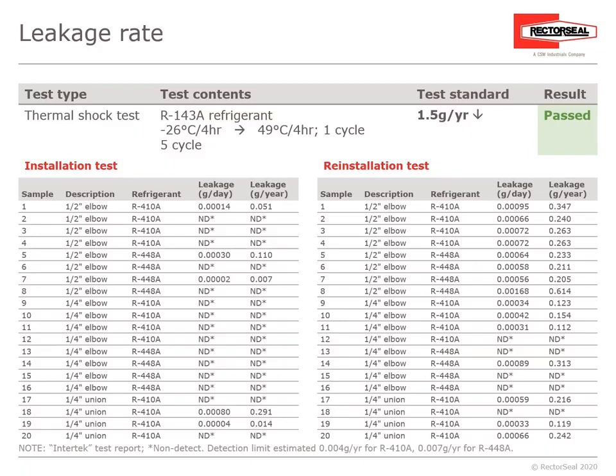Then we took our release tool, separated the copper tubing from the ProFit Quick Connect, reinserted it, again, those same 20 samples, and again, with those refrigerants, and what was the leakage grams per year. Although it did have a slight increase versus the initial installation test, it is still significantly less than the allowable standard of less than 1.5 grams per year.